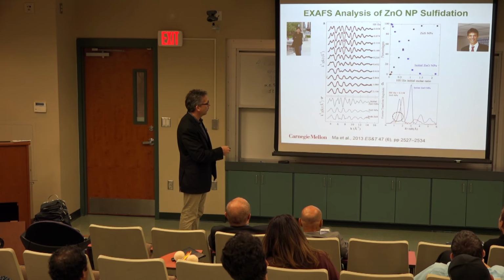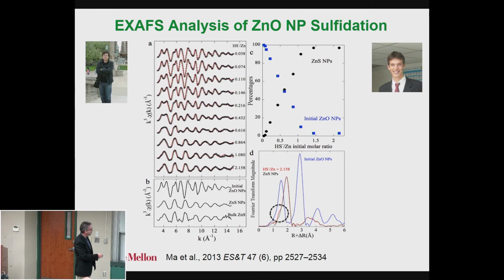Turns out that this looks just like zinc sulfide nanoparticles. That spectrum looks like that one. So you're taking zinc oxide and slowly converting it to zinc sulfide. But we never got to zero. It never went away. There's always this core of zinc oxide, which we can tell from that little hump right there. This one is a zinc-oxygen distance. This is a zinc-sulfur distance. So I can tell that I have a little bit of zinc oxide there.